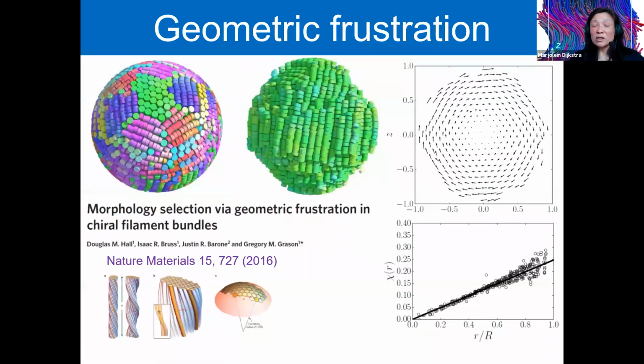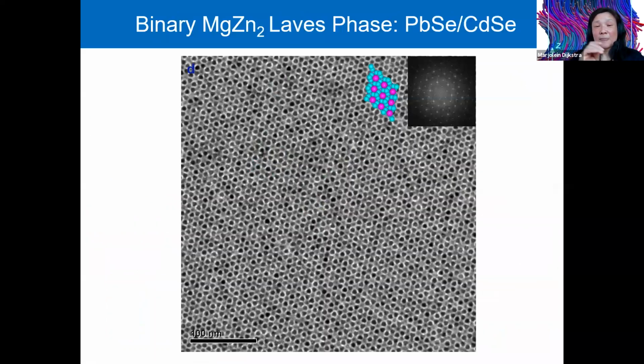One can also look at circular platelets. For that, we find that they also form these stacks or columns of platelets, but we also found a very nice twist or chiral arrangement of all these columns. This is very similar to if you have filaments and you use a geometric frustration due to confinement, you will find that they form chiral structures.